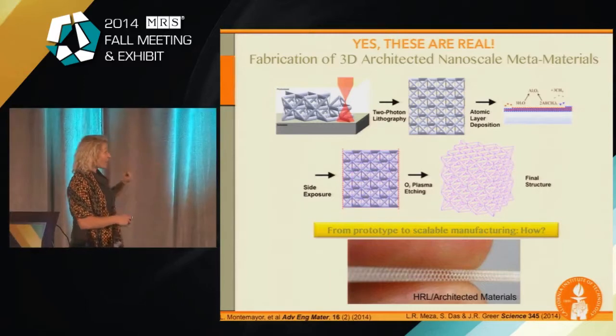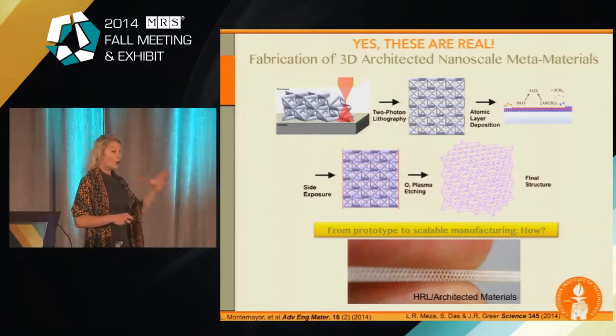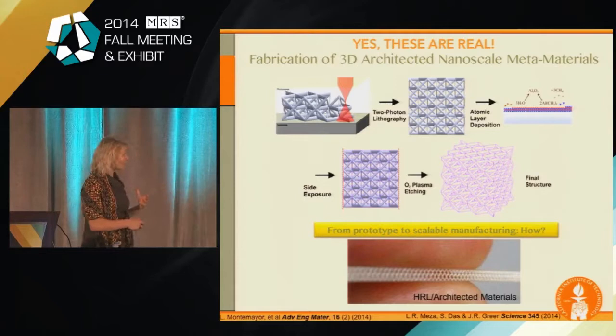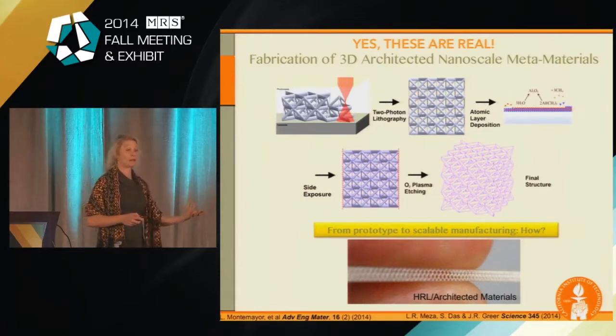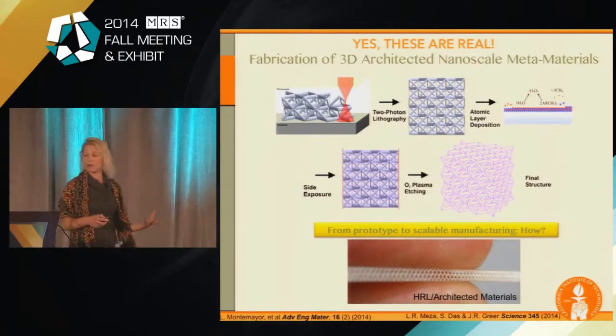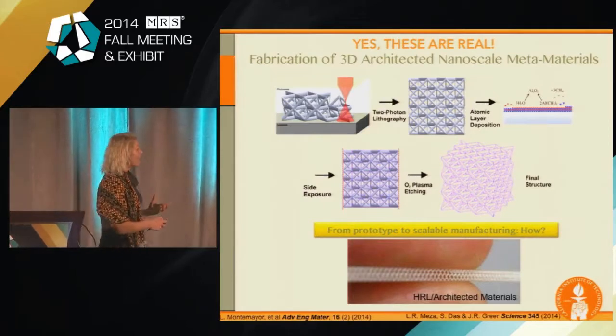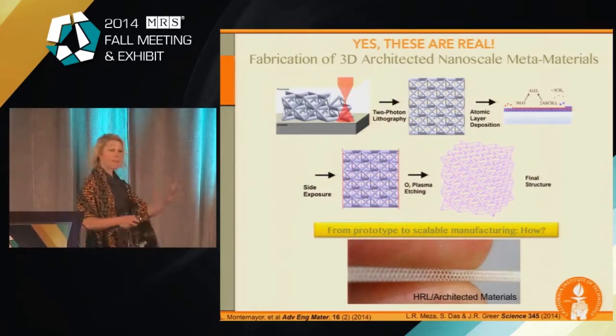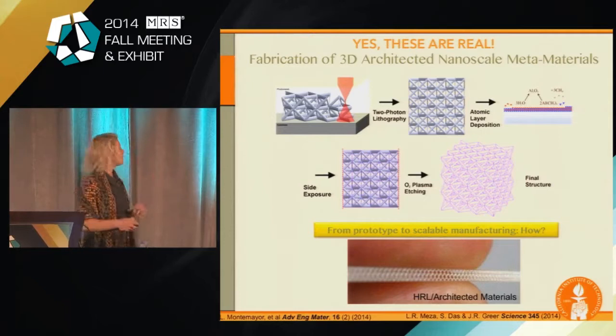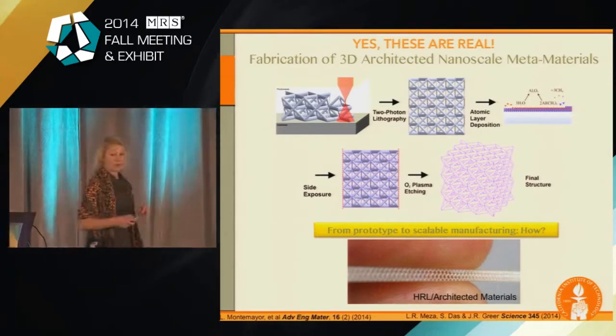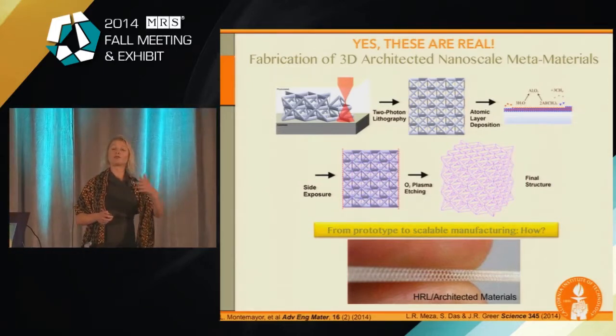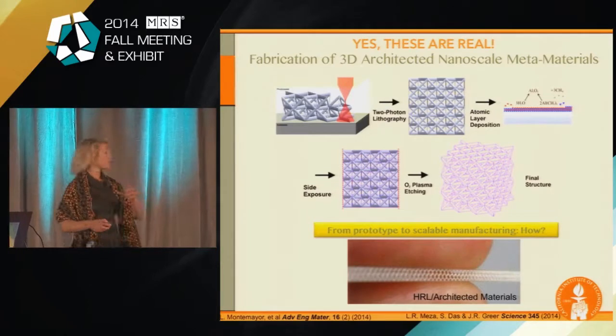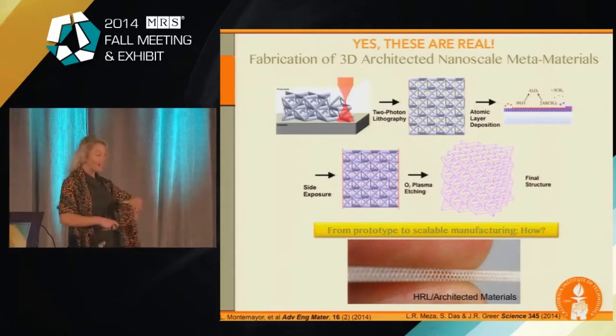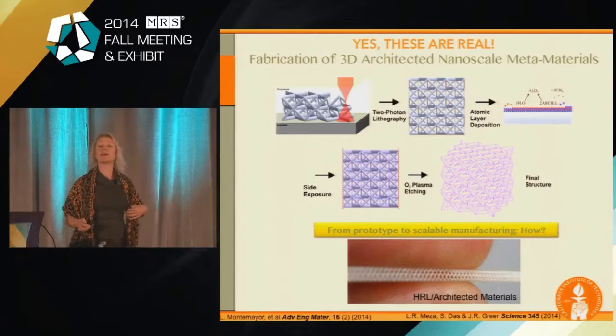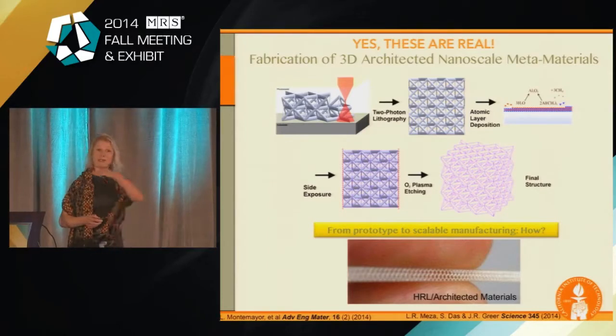So what we do after we've created this polymer skeleton is we coat it with another material. And we coat it with something that is useful for a particular application. And I'll show you some of the applications that we've already embarked upon in our group. In this particular way, for the ceramics that we generated, the ones in the movies that I showed you, we use atomic layer deposition, or ALD, to deposit a conformal layer, like that nano ribbon I was describing. And then we expose the edges and we etch away the polymer. And this is what allows them to be hollow. This is what allows these structures to contain about 99.9% air.